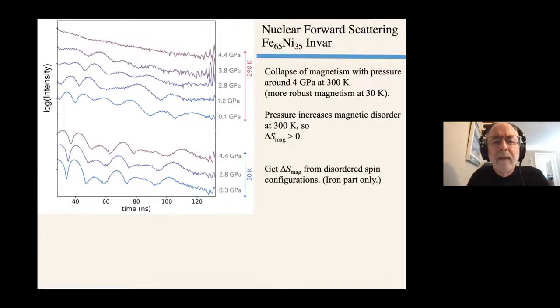Now here's what we have for the nuclear forward scattering. We have these interferences between hyperfine transitions in the material, which are giving a time structure that indicates magnetism when we have a lot of beats. And if this pattern doesn't change too much, then the magnetism isn't changing very much. And that's what's happening at 30 Kelvin. These various dips and peaks are more or less in the same place.